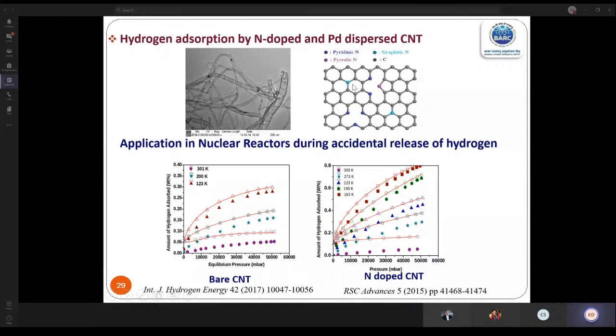So this is the atomic position of carbon, wherefrom we can knock out one carbon atom and place a nitrogen atom. Depending on the placing, it can have pyridinic structure, pyrrolic structure, or graphitic nitrogen structure. And by doping that, what we have seen is that we can improve the interaction with hydrogen. So here I have shown in a graph how with nitrogen doping, the hydrogen adsorption capacity of carbon nanotube has improved. It has a typical application in a nuclear reactor where, during accidental conditions, there is a release of hydrogen.